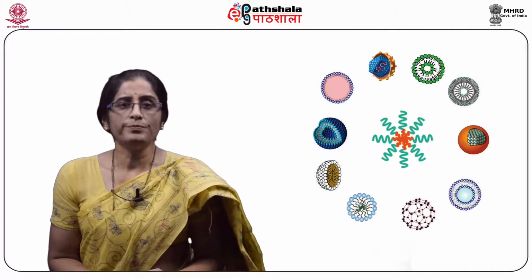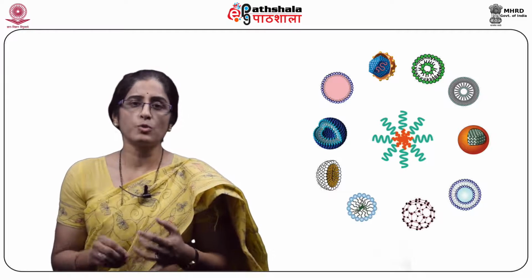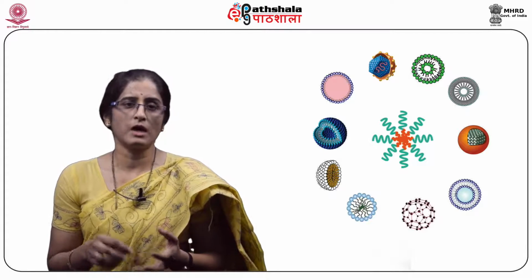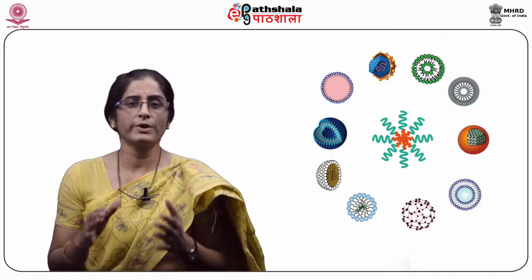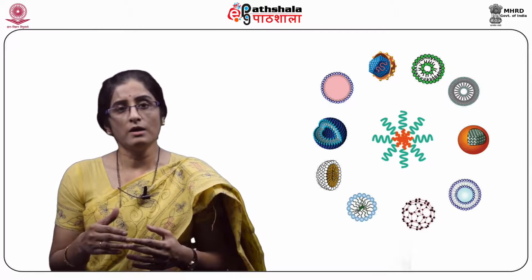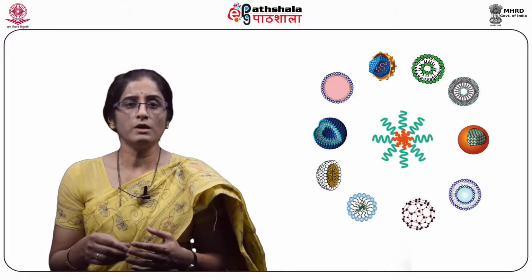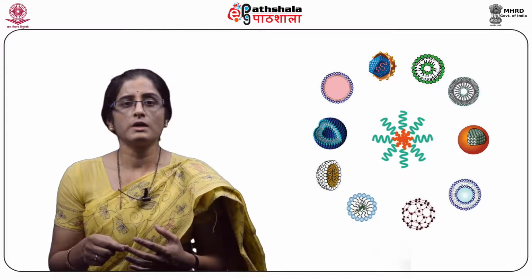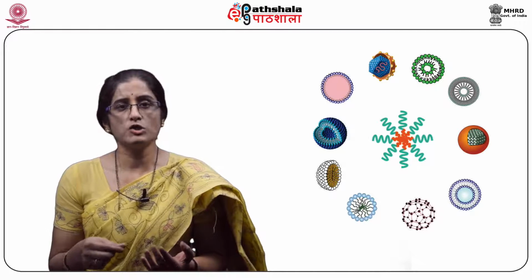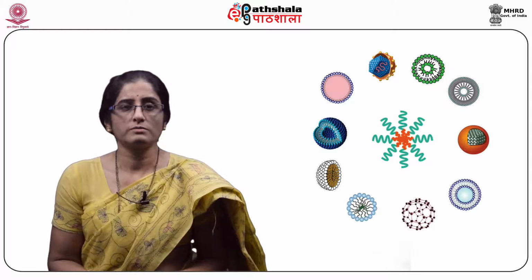Let us take the first technique, rapid expansion of supercritical solution. In this method, the material to be processed is dissolved in a supercritical fluid such as carbon dioxide in a high pressure mixing cell. The solution is then pumped into the pre-expansion unit using a syringe pump and is heated isobarically to the pre-expansion temperature.